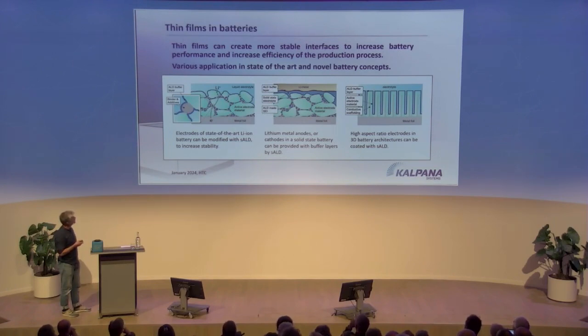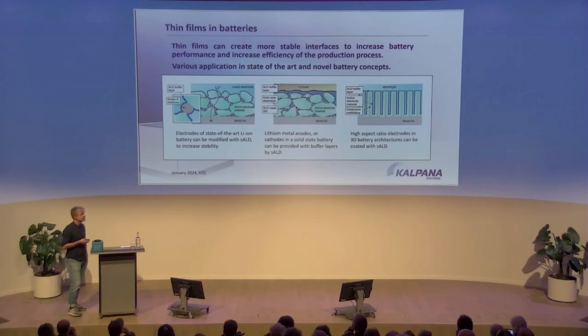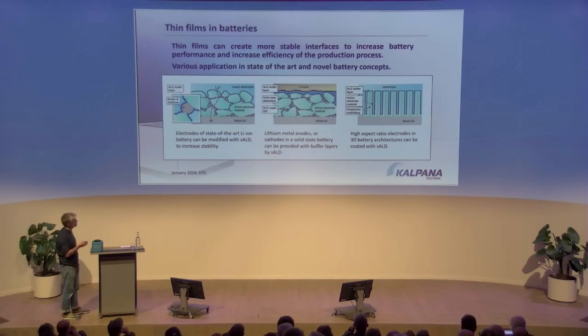And looking at novel battery concepts, so maybe you want to use a pure lithium metal anode, there's also a good function for a thin film application, because lithium is very reactive with air and water, so you might want to add a buffer layer to that. Or going into high aspect ratio battery concepts, this of course looks very much like what LionVolt does. Apparently LionVolt is also present, I don't know. There you deliberately increase the surface area in your battery, which makes it even more important to make this thin film interface, to give it the right characteristics.